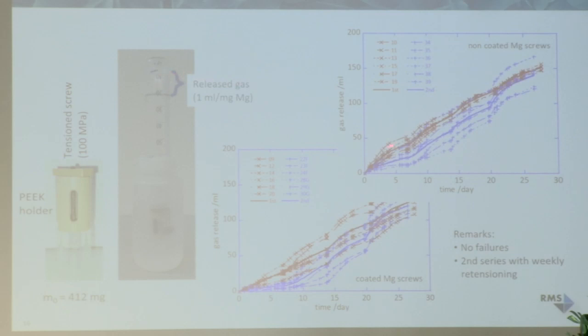What you see here is the released gas over time. So this is over 4 weeks. Every week we change the liquid. And you see that within 4 weeks, about 100 to 150 milliliter of gas. That means 100 to 150 milligrams are degraded. The initial weight of the screw is about 400 milligrams.